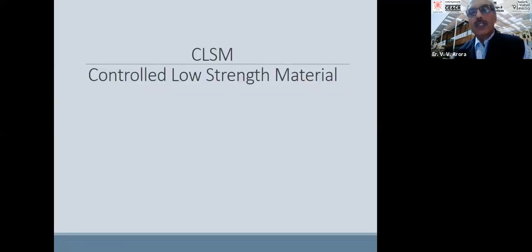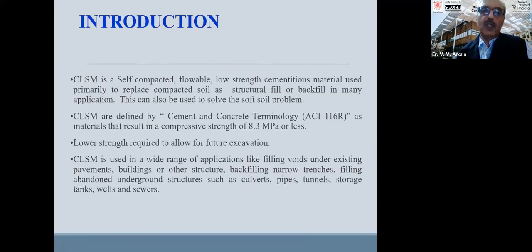Another is controlled low strength material. This is for backfilling, where we can dig and fill it. We don't have to compact it; it is self-compacting, self-compactable, flowable, low strength cementitious material. In the cement and concrete terminology, ACI has got a complete report on that, not a specification, but a report. The strength is around 8.3 MPa or lesser. It's a low strength material.